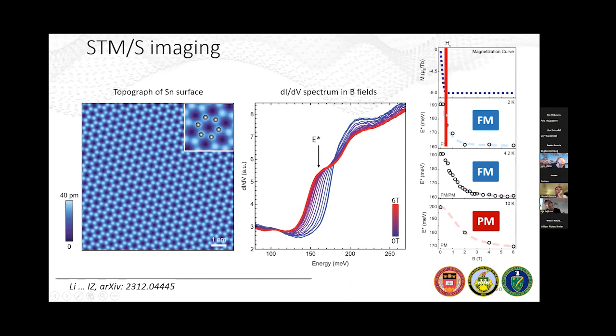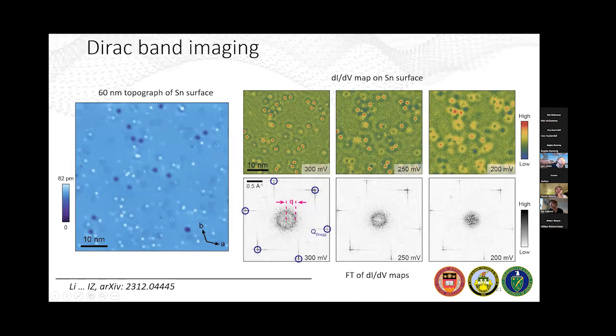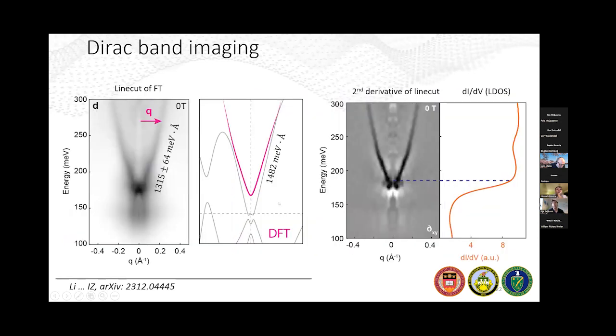So the HC here is about maybe half a Tesla, but here we have the dispersion to about 2 Tesla, even more at this higher temperature. So we wanted to investigate this further, and then we performed the same QPI measurements. Again, you see a circular pattern in the center of the Fourier transform that disperses as a function of energy. We plot in terms of this radially averaged Fourier transform.